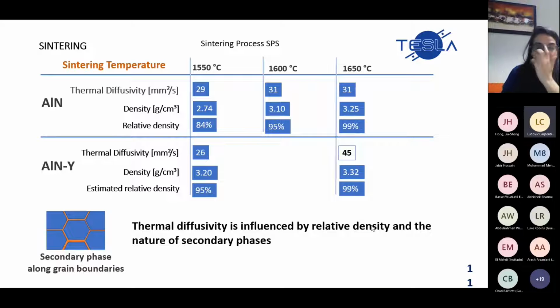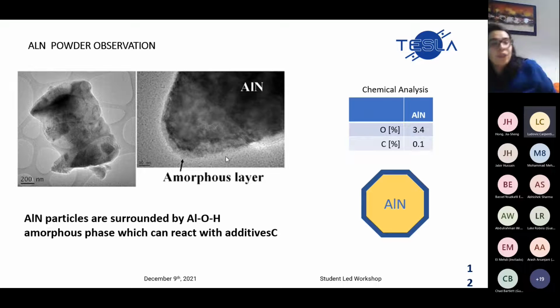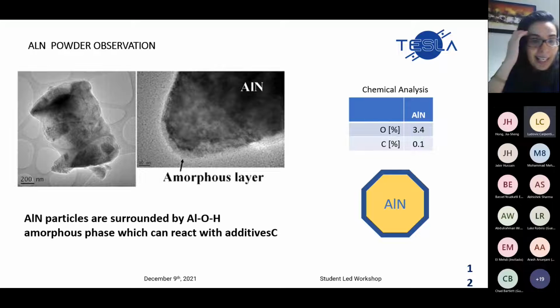So it will impact the properties. If the secondary phases were in triple points, you would more likely reach different properties than the ones shown here. Okay. I also did some observations of the particles by TEM. We found that the particles are surrounded by an amorphous layer of hydroxide compound, which could react, which helps in a sense with the sintering.